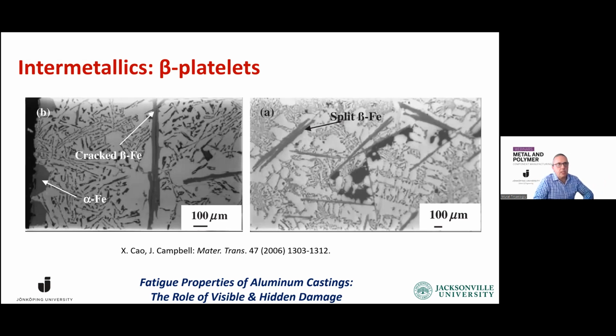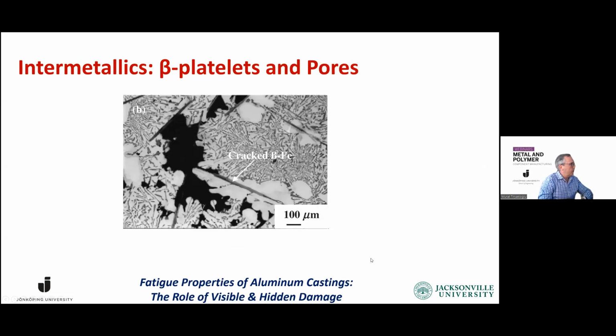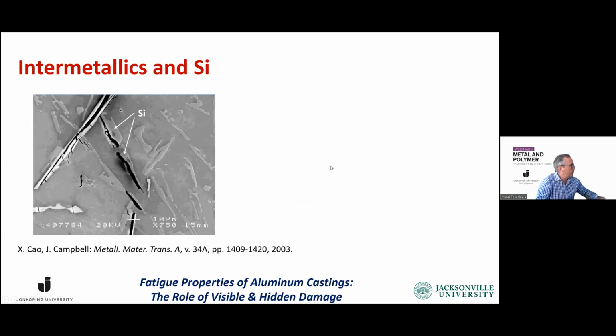In most examples, not all, but you can clearly see a crack right through them, or they are split. And if we continue, they can be around pores, and they are known to affect the feeding of the liquid metal around the pore, but they can be associated with pores. But they usually have cracks right in the middle. And I'm going to show you one more.